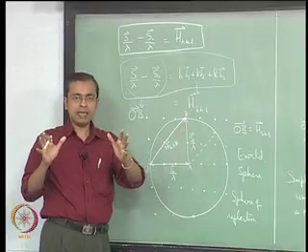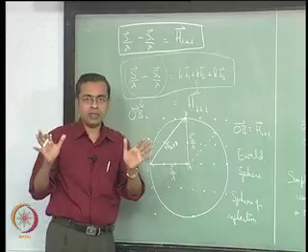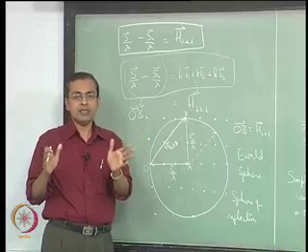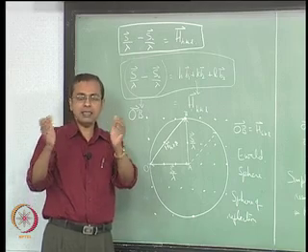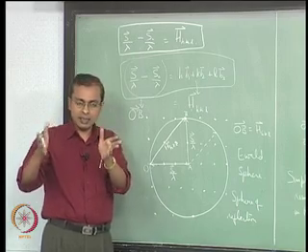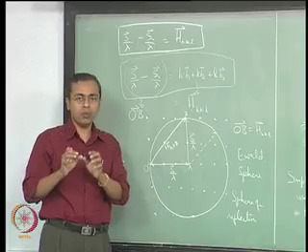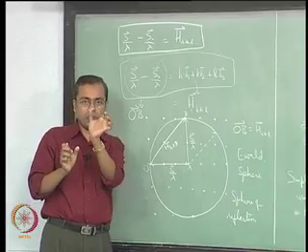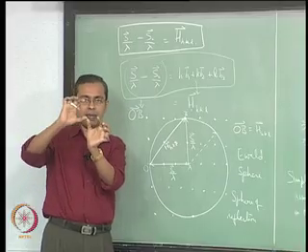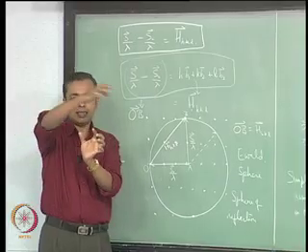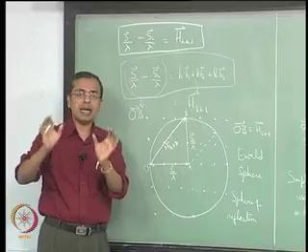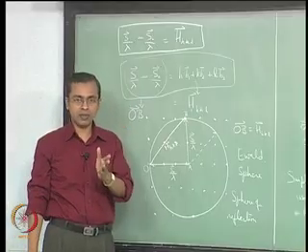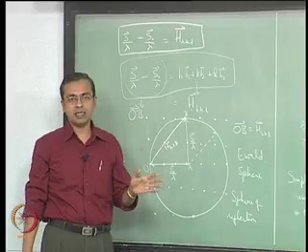This same material, if you want to understand how it is interacting with waves, especially electromagnetic waves, we will have to first represent this in reciprocal space. Its representation in reciprocal space will continue to be a simple cube, except that the dimensions will now be 1 by A. So you will make 1 by A, 1 by A and 1 by A in 3 directions, and you will build the lattice. Now that is the reciprocal lattice of the original material you were interested in. Whatever the original material, you have now created its reciprocal lattice.